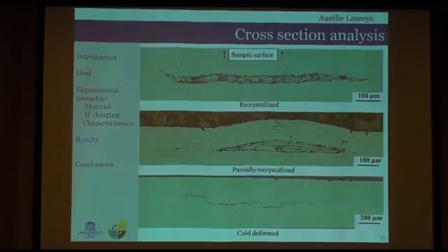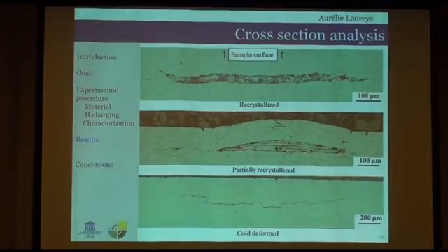If we then look at cross sections, we found this result. What the different materials had in common was that the cracks mostly went parallel to the surface, and also the crack tips often deviated towards the surface. So this is an indication of the internal pressure theory, because cracks will move towards the surface to release their internal pressure. Additionally, we saw that the cracks, in all cases, were not common single cracks, but consisted of interconnecting, branching, small fine hairline cracks, and always recombined to form one bigger crack entity.